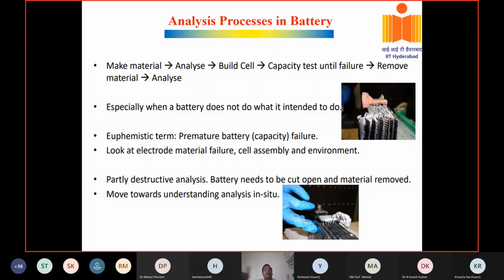And also during operation of the cell, you can do impedance: first cycle, 100 cycles, 500 cycles, 1000 cycles, so that you will know the increase in impedance. If my impedance is increasing drastically, that means my cell may be going to fail. Capacity is going to fall. The life of the battery is going to fall. So like this, you can understand many aspects.